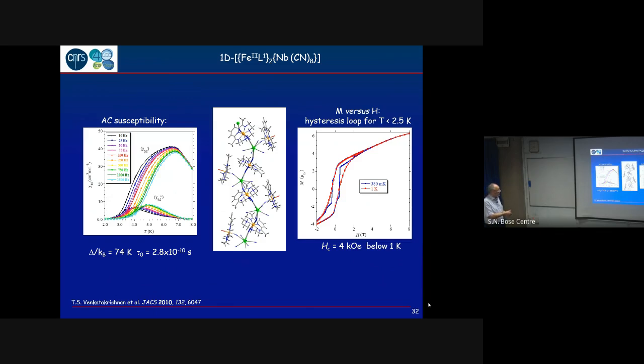So here, this is what I have discussed before. This is an out of phase signal, so it's typical for slow relaxation of the magnetization. And another feature for the blocking of the magnetization is magnetic hysteresis. This is shown here. So for this compound, we could see that below or at 1K, we have a magnetic hysteresis. In this plot, what I show is the magnetization versus H in one direction, and the applied field in the other direction. And you see when you go up, down, you do not follow exactly the same. So for this system, we have the hysteresis that tells you that you have a bistability.